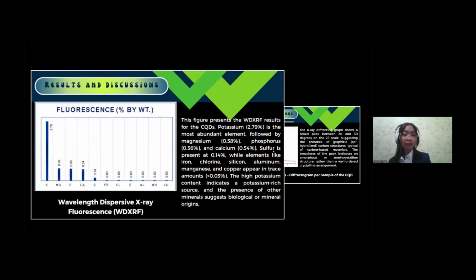The figure shows the heavy metal analysis of the CQDs. Potassium is the most common element with about 2.79%, followed by smaller amounts of magnesium, phosphorus, and calcium. There are also traces of sulfur and tiny traces of iron, chlorine, silicon, aluminum, manganese, and copper. The high potassium level makes sense since the source is rich in potassium, and the other elements come from natural minerals or biological material. Now we move on to the results of the experimentation.